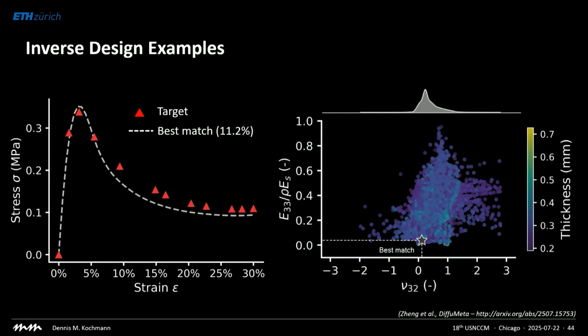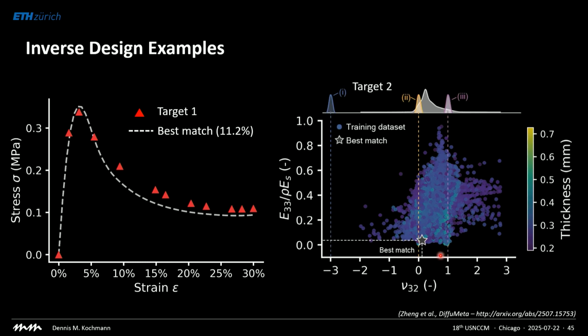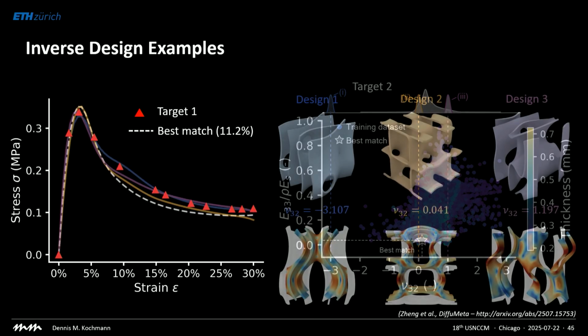Like I said, you can also do multi-objective optimization. So let's say I come and I say I want a stress-strain curve that looks like this. The best match in the training set is actually fairly close. But let's say we want a second objective. I want the structure to have a very particular Poisson's ratio so that it deforms in a certain way in the transverse directions. If I look at the best match from the training set that has a Poisson's ratio close to 0, let's throw in a second target, and let's say I want 3 different structures. They're all supposed to have this stress-strain curve. One of them is supposed to be very auxetic, having a negative Poisson's ratio of -3, one close to 0, and one close to 1. Keep in mind this is anisotropic, so the classical bounds don't apply here. If you run it through the diffusion network, what you get is this.